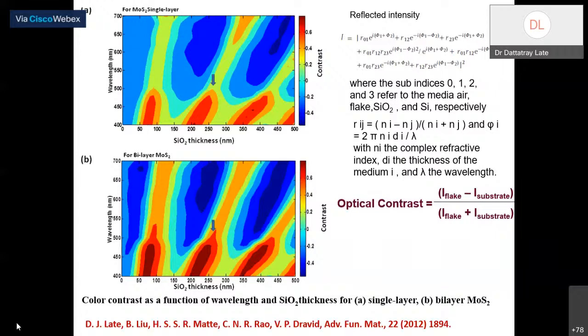Again, you go for a bilayer of MoS2, in the bottom left image, SiO2 thickness as a function of this wavelength, right? See, this is a very simple equation. You can solve this equation and define what color you are expecting for a single layer of MoS2 or any other layer of chalcogenide, MoS2, WS2.